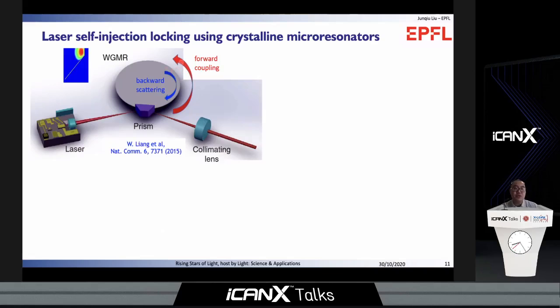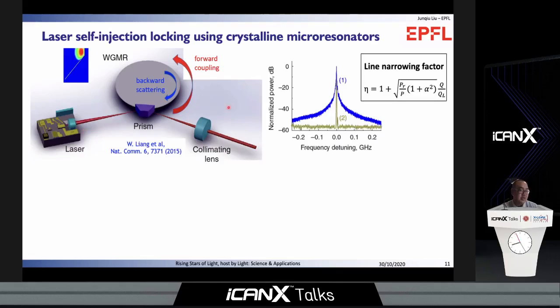However, due to surface and bulk scattering, there is a tiny portion of light in the back reflection, which is sent back to the laser. This backscattered light can trigger the laser self-injection locking that modifies the laser linewidth dynamics. In the end, the laser linewidth reduces